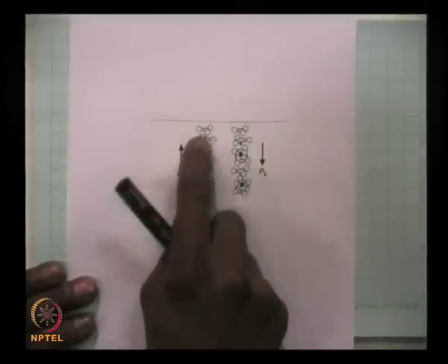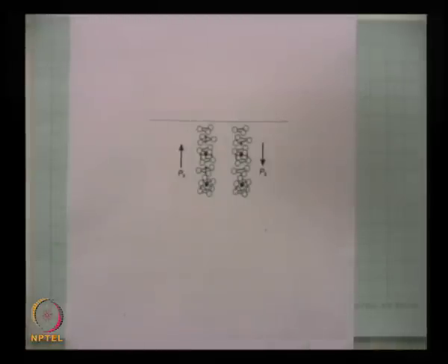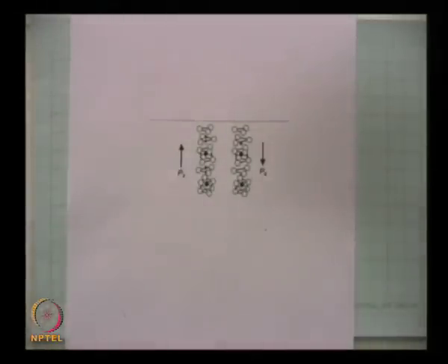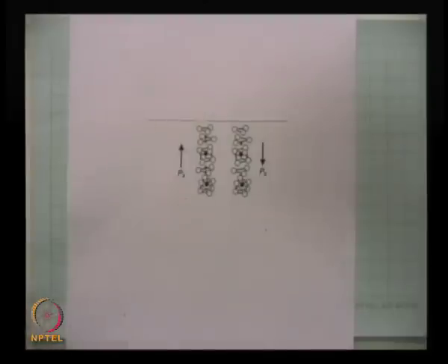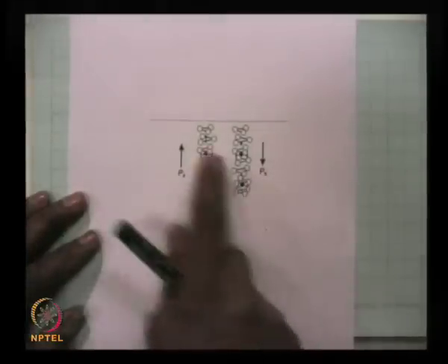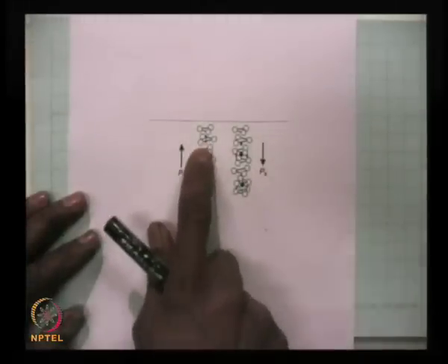Actually, if you heat it to the Curie temperature, the position of the lithium comes onto the plane of the oxygen atoms, and so there is no axis then; the axis is just gone. Now, this spontaneous polarization is connected to the coefficient of the D tensor and the axis of the crystal. So to reverse the sign of the nonlinear polarization, I need to push the lithium ion across the plane below.